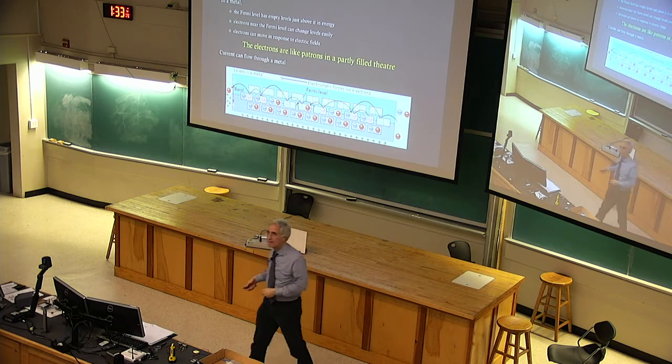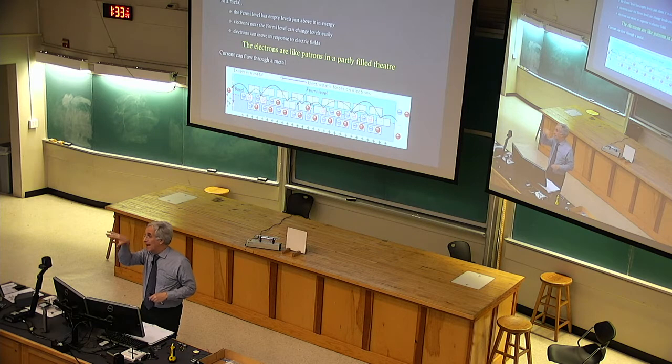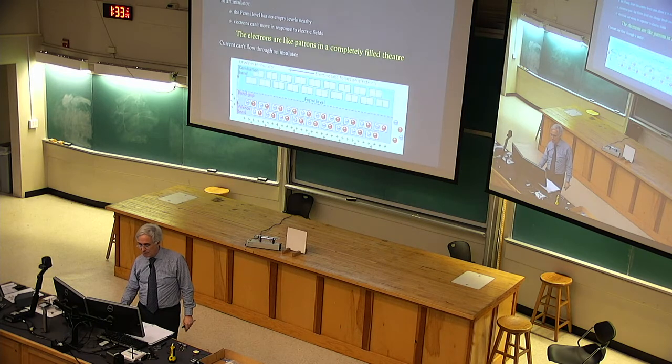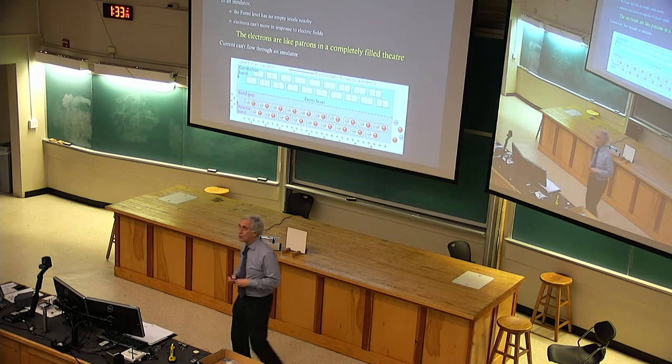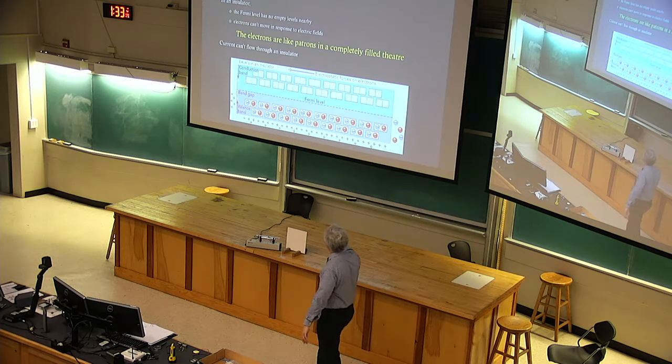Just to name it, Fermi level. The Fermi level in a metal occurs somewhere in the middle of a band, because you haven't finished filling. In contrast, the Fermi level in an insulator occurs between bands. We've filled all these levels down here in this band of levels, the so-called valence band, and we have not yet filled any of the levels.